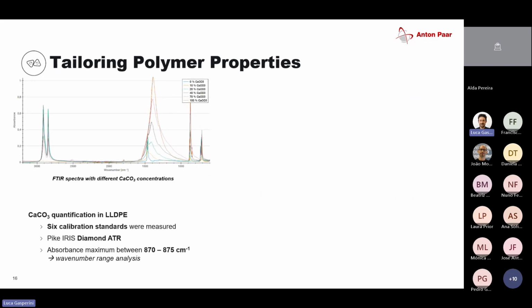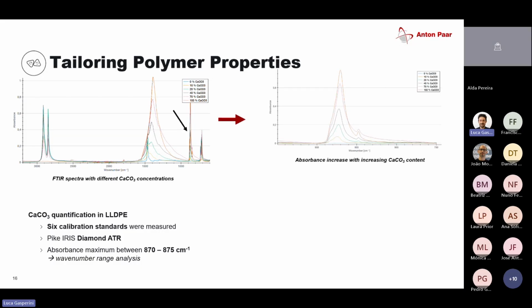So for example, here we have a spectrum of PE with different concentrations of calcium carbonate. As you can see here, typically you would not have these peaks here, and it's not very user-friendly to look at it. So what we did, we isolated this specific peak. So what are we looking for? We're looking for a peak that changes with the concentration. Responds linearly to the concentration. Yes. So in this case here, if you take a look here, this is 0% calcium carbonate.